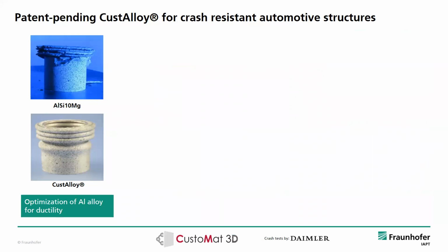So when looking into automotive applications, we didn't want to optimize for strength, but for ductility. And we're very content to have a patent pending alloy, CustAlloy, which we developed in the CustoMat 3D consortium. Here you see a comparison of a crash test for aluminum silicon 10, where you have a brittle crash and failure of the material, spatters flying around. And in the CustAlloy, you see a really smooth bending of the structure in the crash test.